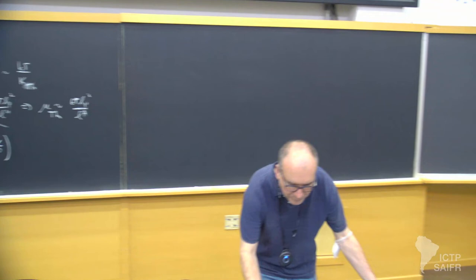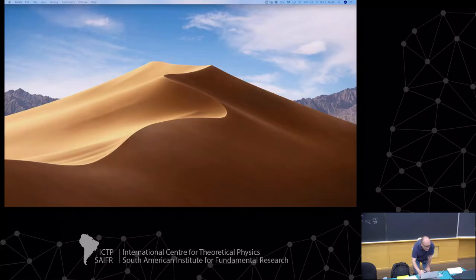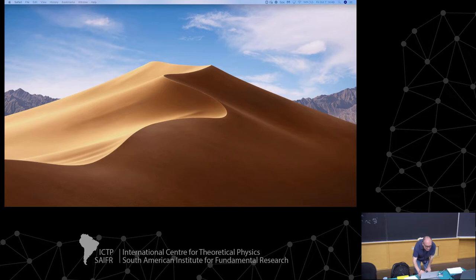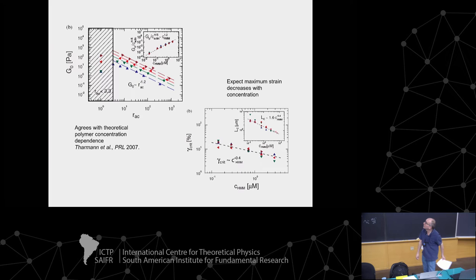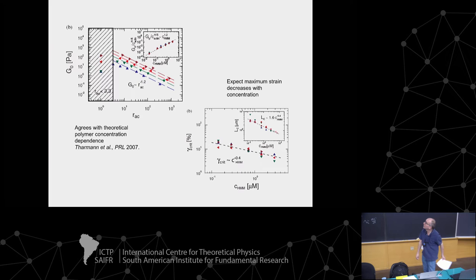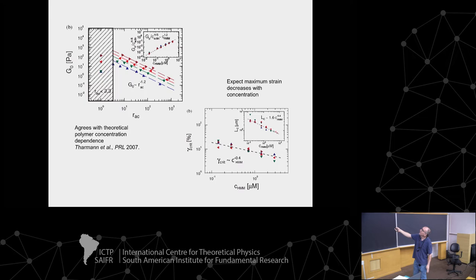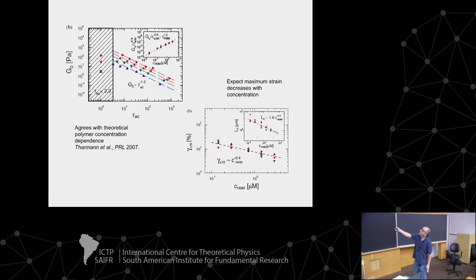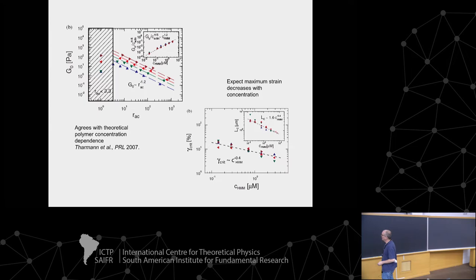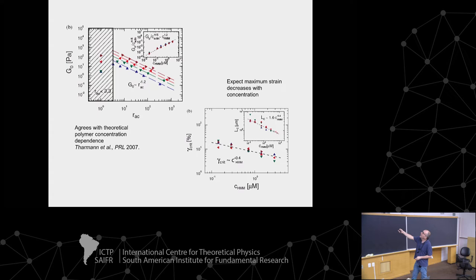Let me show you that this actually does account for some experiments — from a group in Munich, the Bausch group, a little over a decade ago. The inset shows quite nicely that the collapse of the data is basically an indication that the shear modulus is growing with the 11/5 power with concentration — a slightly odd exponent, but the result of a calculation you can do more carefully.